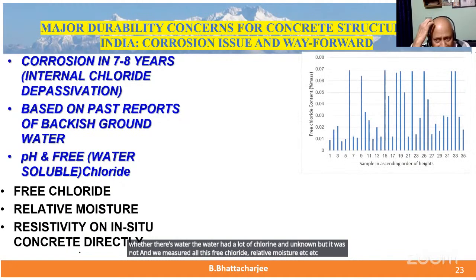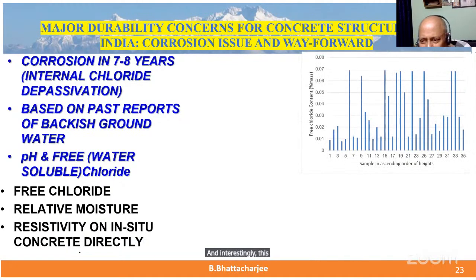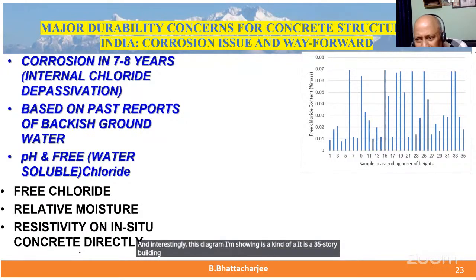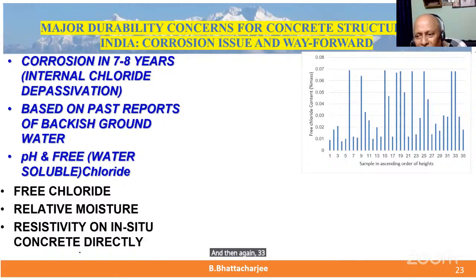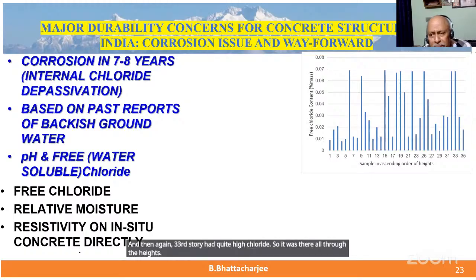And interestingly, this diagram I'm showing is of a 35-story building, not one, several of them, I picked up from one. And you have chloride content as you go from the bottom. The 7th story and 6th story had pretty high chloride. And then again, the 33rd story had quite high chloride. So it was there all through the heights, right?